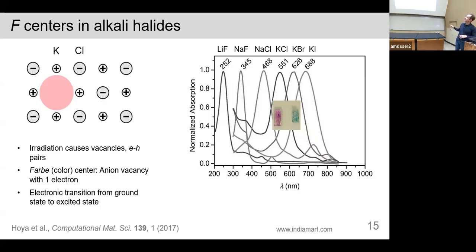And lithium fluoride has the smallest lattice constant, so it's the most confined well. And so it has the highest energy. And that's like 252 nanometers, which is way in the UV, the deep UV. And then you can go all the way down to 688, which is like deep red for the large crystal.